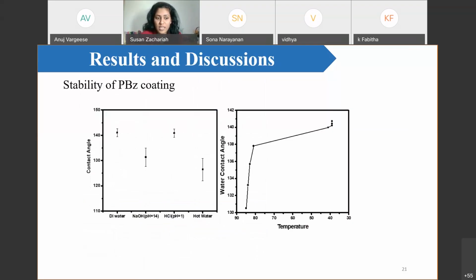Like the contact angle checked with DI water, NaOH, HCl, hot water. Whenever we use NaOH on the surface, the contact angle reduces, and once we use an acid, the contact angle increases. We also checked the property when we heat the sample, and even in a harsh environment and heat, it finally gave a good contact angle above 145.